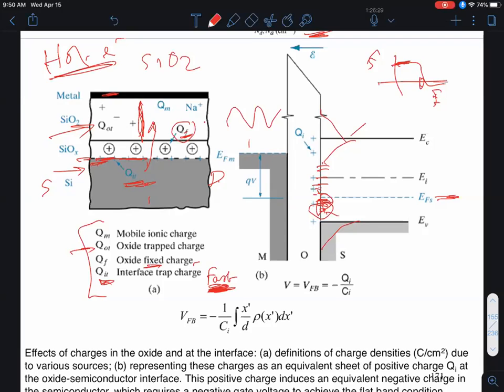The reason ICs don't last forever, they're typically designed to last for maybe 10 years or so, is because of this hot electron generation or hot hole generation, which can be trapped in the oxide, and over time, you change the electrical properties, you change the flat band voltage, therefore the threshold voltage, and therefore at some point the circuit fails, okay? And the typical design time window is about 10 years. But it turns out, these days we get rid of our iPhones or laptops way before 10 years. In most cases, it's not a practical limitation, okay?